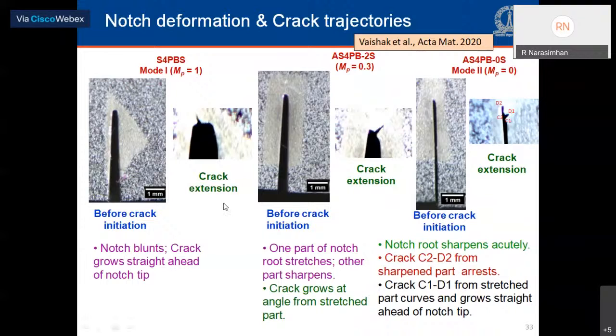We can make that out from optical metallographs, which I have shown here for the mode 1 specimen on the left side, the mixed mode specimen in the middle, and the mode 2 specimen on the right. If you look at the mode 1 specimen, the notch blunts symmetrically, and the crack initiates at the original notch tip and goes straight. In the mixed mode case, one portion of the notch root sharpens and the other portion stretches. The crack initiates in the stretched part and then grows at an angle, as you can see in the right side middle image.